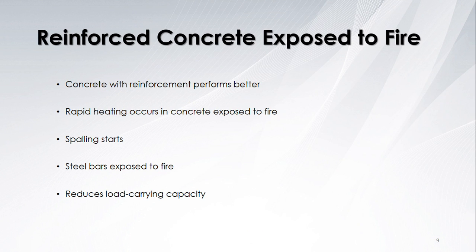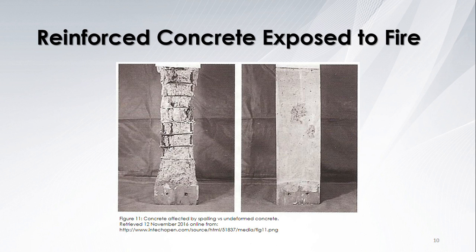Generally, reinforced concrete performs better under loading in comparison to non-reinforced concrete. The reinforcing steel provides ductility when it yields. When the concrete is exposed to fire, it heats up at a rapid pace. This rapid heating can cause explosive spalling in the outer concrete layer, which will expose the reinforcing steel to the fire. Once the steel is exposed to fire, it will heat very quickly. Extensive damage in the structure can occur, causing total failure or collapse. The picture on the left shows concrete that has spalled, exposing the reinforcement due to a rapid temperature increase, while the picture on the right shows concrete exposed to fire without spalling occurring.